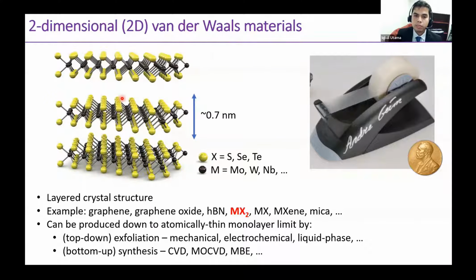And because it's weak, it's possible to cleave these layered crystals into their ultimate thinness limit, which is just a single monoatomic layer. For example, in this schematic, I have transition metal dichalcogenides, where the yellow atoms are chalcogens, such as sulfur, selenium, tellurium, and the middle atoms colored in black are transition metals, such as molybdenum, tungsten, niobium, and so on. A monoatomic layer of these two-dimensional materials is very thin. It's only 0.7 nanometer in the case of tungsten diselenide, or maybe even thinner in the case of a single atomic layer of carbon, which is called graphene.